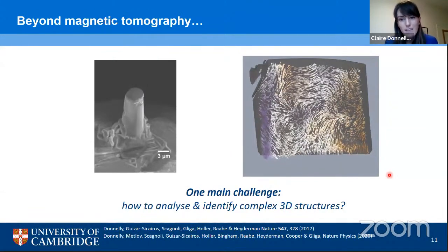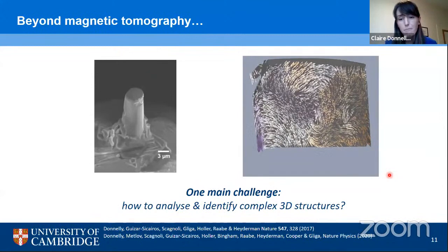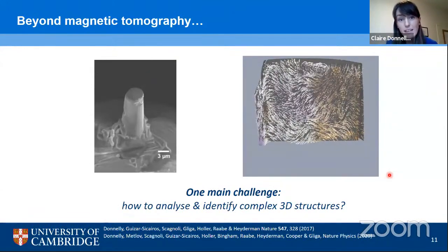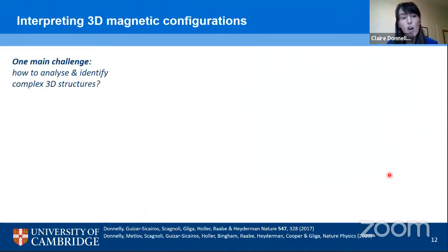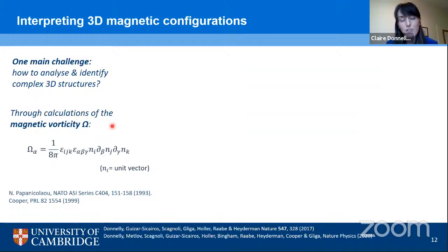In order to address this challenge, we have recently implemented a new type of data analysis for these 3D configurations, which implements a calculation of the magnetic vorticity vector. Now, I've put this equation up here on the slide for those of you who are interested, but essentially the magnetic vorticity vector represents the flux of the skyrmion number density, meaning that it encodes the topology of our magnetic configuration. So we can first of all consider a couple of basic topological structures.